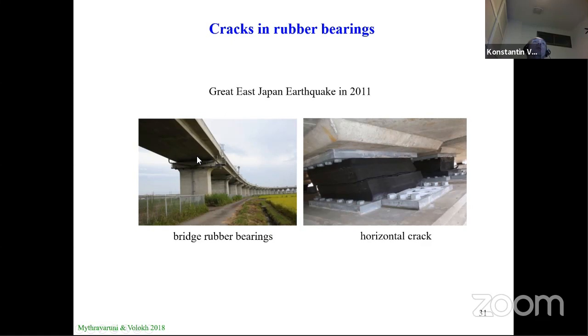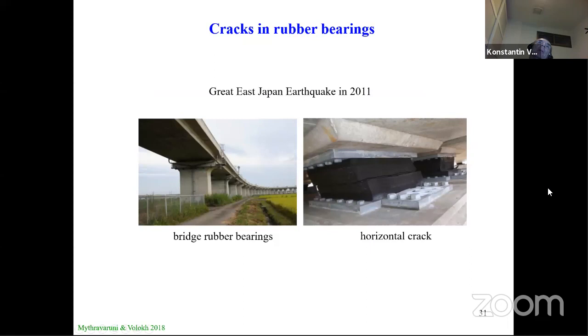As an example: bridge rubber bearings in Japan were cracked during the 2011 earthquake. These bearings helped but they were cracked — with a clear, very nice horizontal crack. In a paper with Mythravaruni and Volokh, we considered simultaneous compression and shear under large deformations and found that the cracks should be horizontal — we could predict these horizontal cracks. This is very interesting because if you can predict the correct crack direction, you can also think about reinforcement — how to reinforce the material and make a composite of it.